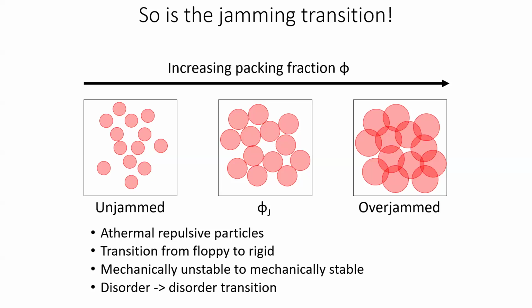So anything I forgot to say here? The model is just athermal repulsive particles. It's this transition from floppy to rigid. But again, it is a transition from disordered to disordered. And so the fact that it is a disorder to disorder transition, where you go from a flowing state to a rigid state, suggests that this is the zero temperature version of this glass transition.